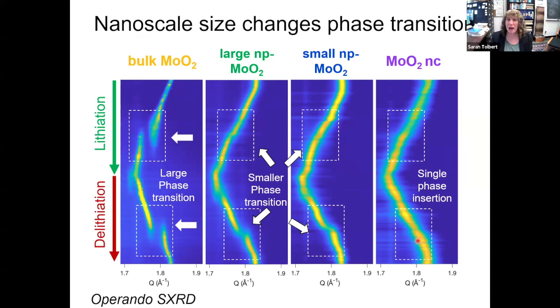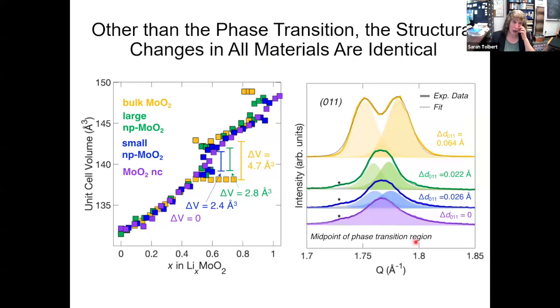Okay, so we can use this data and we can actually just say, what's the volume of the material? And what we find is as we put in lithium, the volume gets bigger. That makes sense. We put stuff in, it takes more space. And all of the materials, big, small, medium, are exactly the same until we get to the phase transition. At the phase transition, the biggest sample has a big jump. The medium samples have a small jump, and the small sample has no jump at all. This is a second phase transition, which does the same. And this is the raw data used to generate this. What this suggests is that in this region, all of these materials should be the same. And in this region, the big materials should be much slower and the small materials should be much faster.